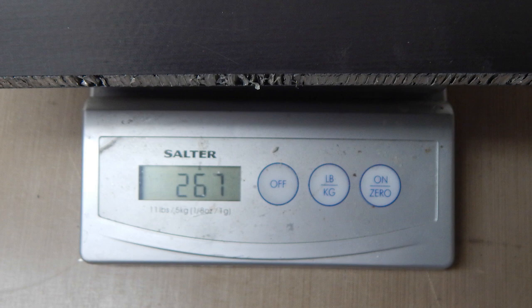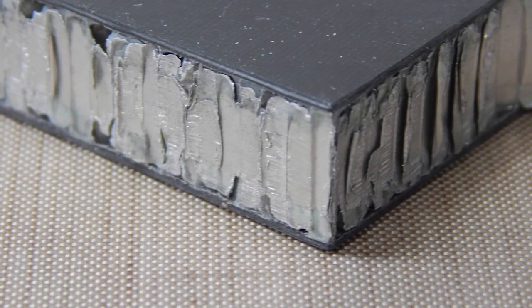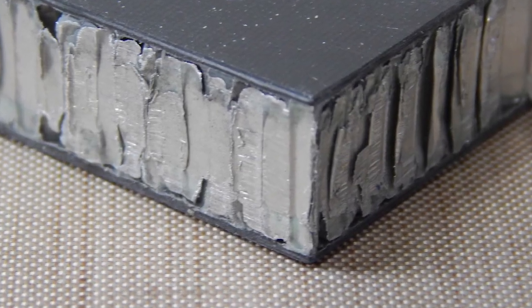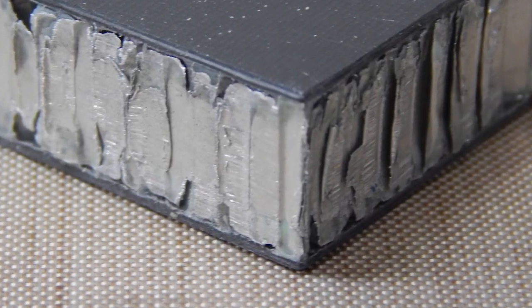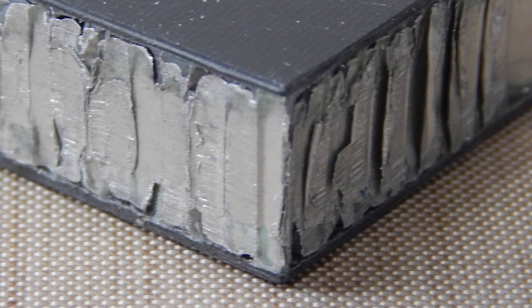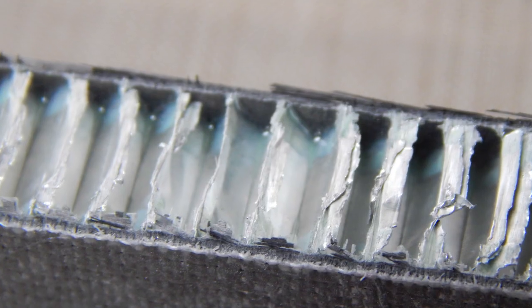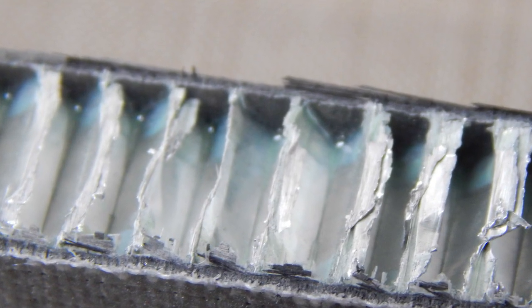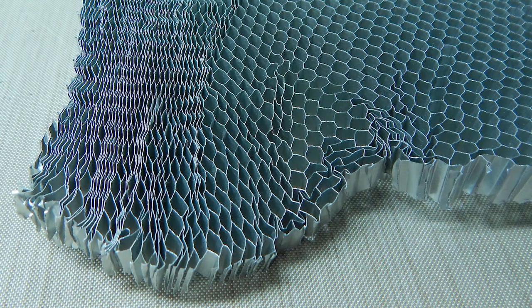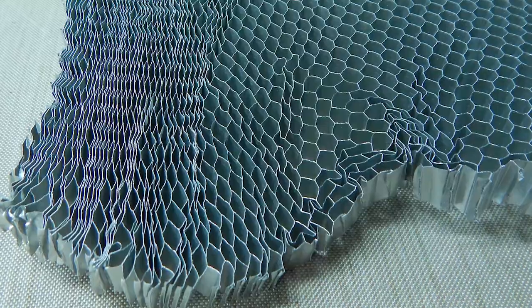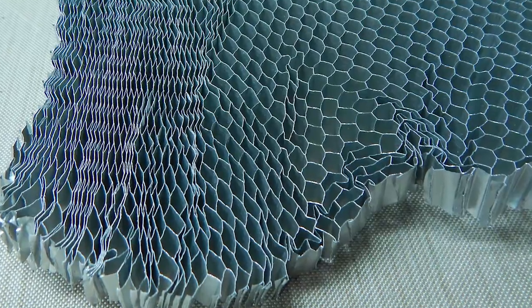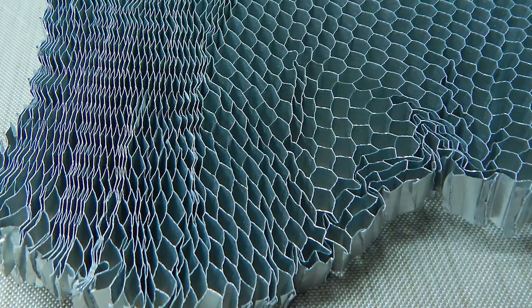And overall weight, nine and three-eighths ounces, 267 grams, which is near what we estimated. And I trimmed it up with a router. And you can see how the router kind of smudged the edge here. It looked a lot nicer where it was cut like this. And you can see the little glue fillets in there that have worked their way up the cell walls. And that's one of the awesome things about honeycomb. Besides squishing and playing with it, is that it really sticks and has got excellent mechanical properties.